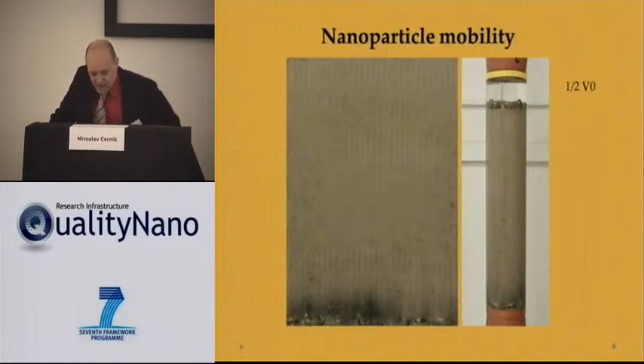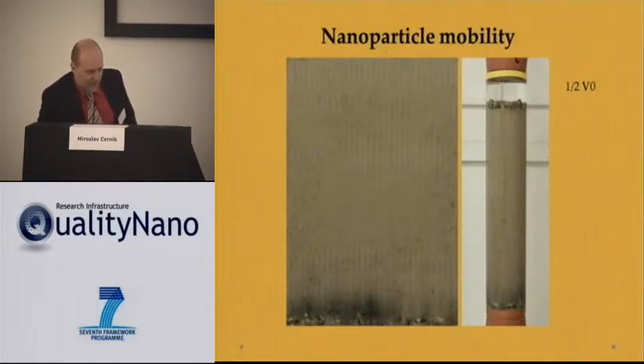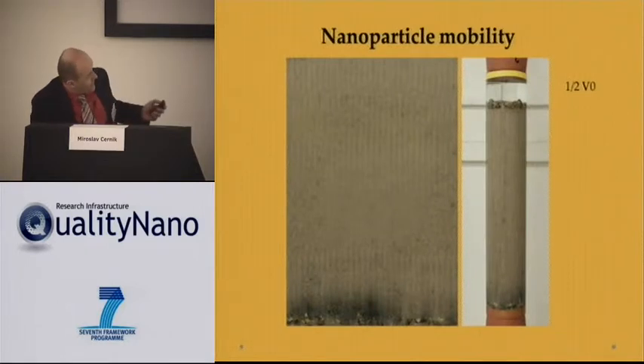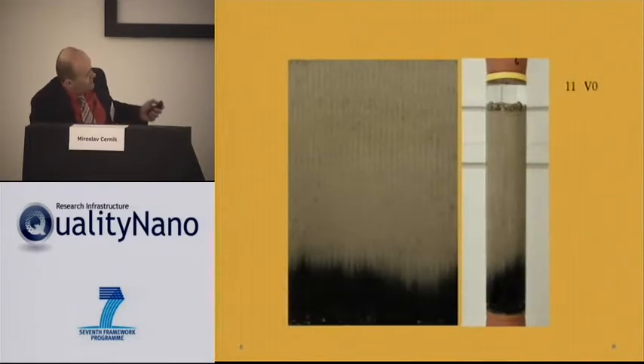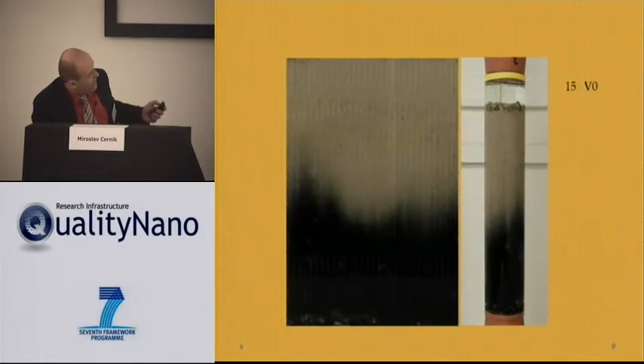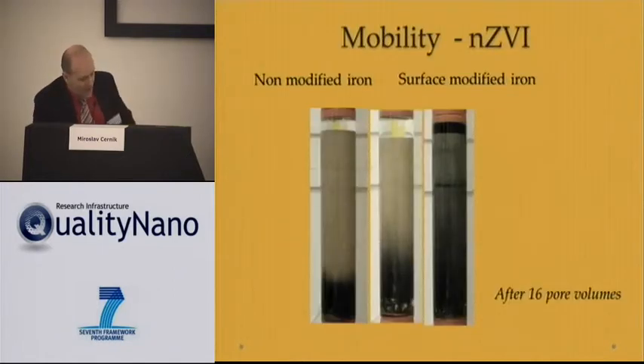So I said that the reactivity of the particles is one thing. The other important parameter is the mobility, and I have here some pictures of how the particle migrates through the laboratory column. Here is the comparison of the non-modified iron and 2 different surface modifications, and you see that by the modification we are able to improve the mobility of the particles significantly, which is the rightmost picture.